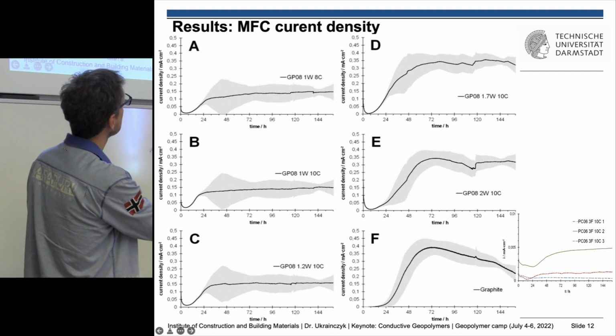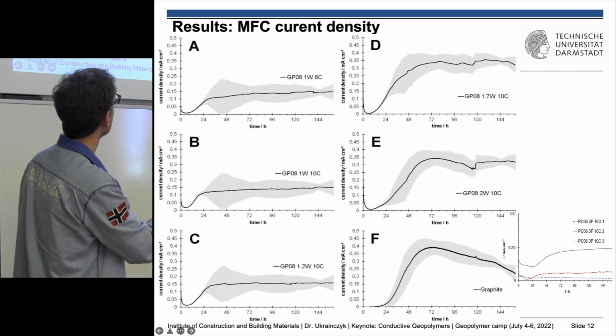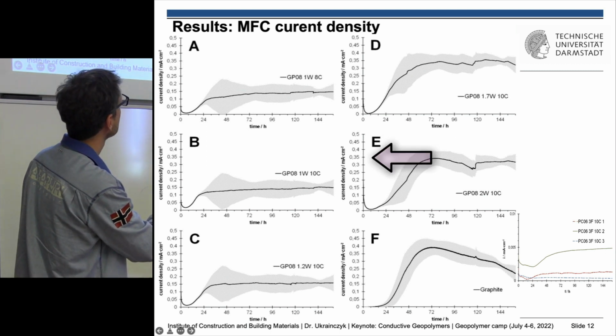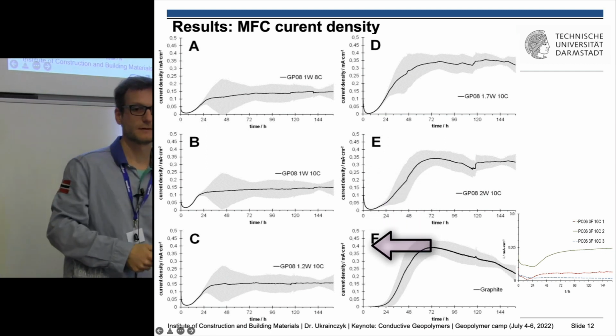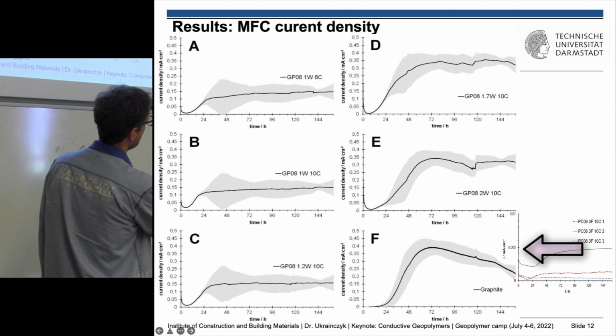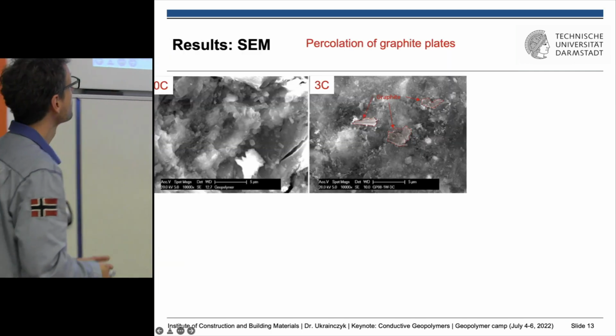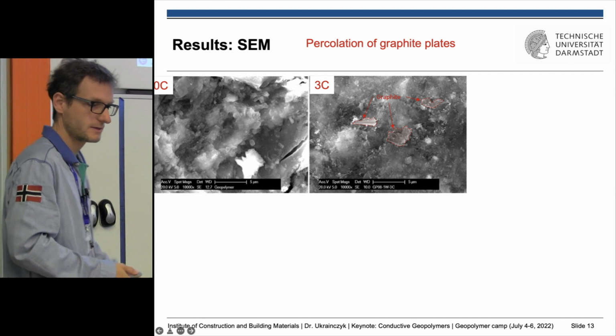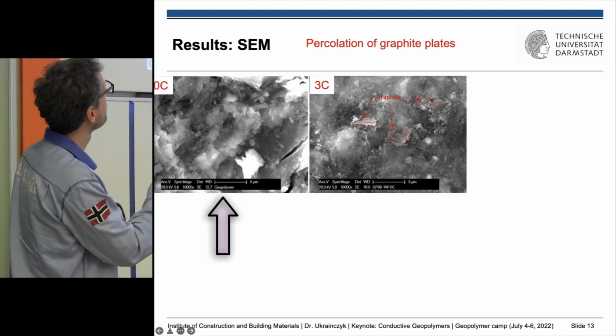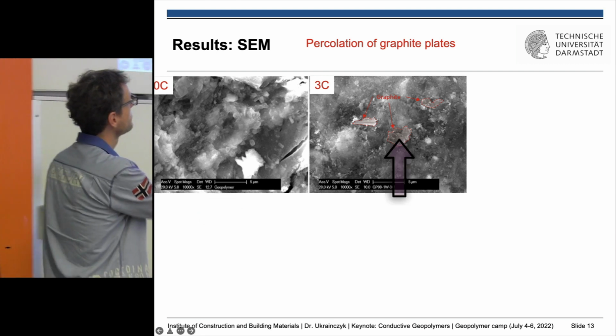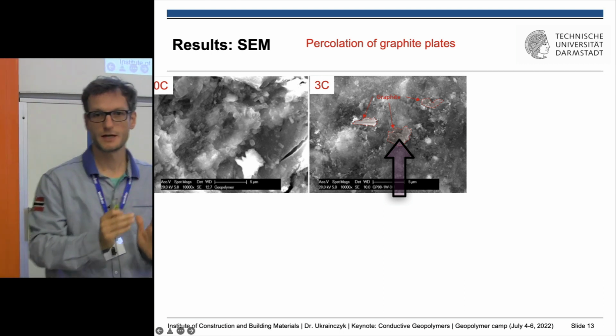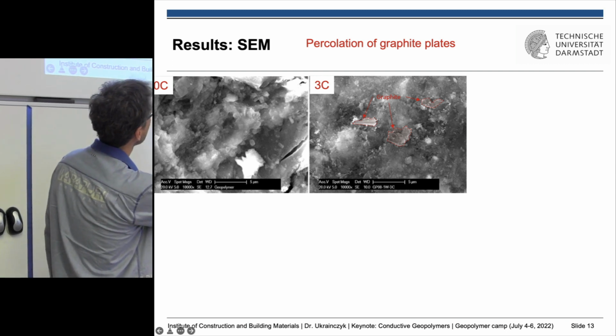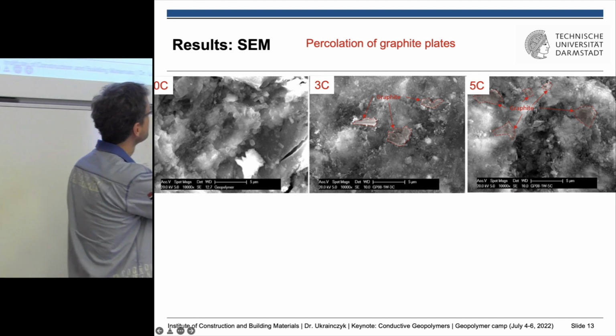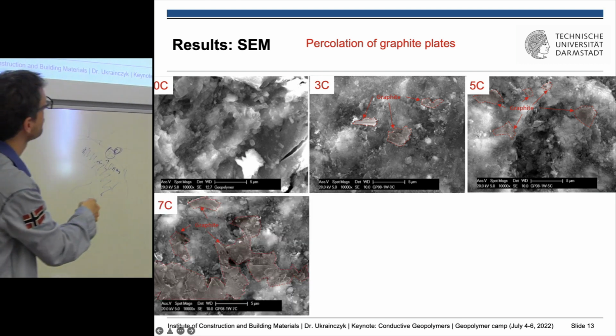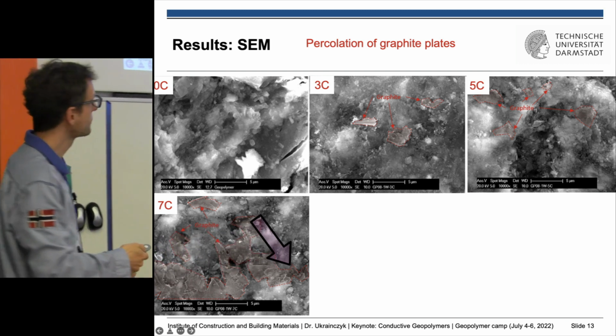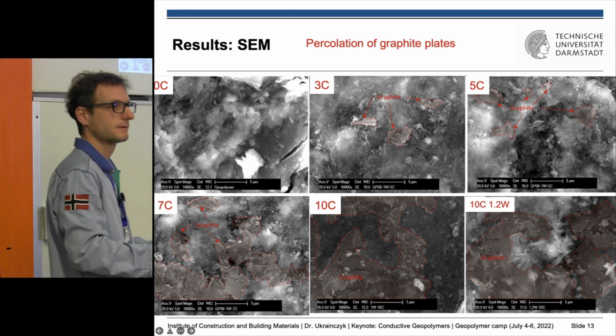So this is the power, the current density around up to 0.4 roughly. And we can see that we reach quite approaching the performance of the graphite reference. For Portland cements, it's really almost nothing, almost zero, 0.005. So now we took some images to see how this graphite percolates. And you can see, this is without graphite. And then we identify the graphite particles because of the edge shape and also the plate structure. And hope you can see them here. But then by increasing the percentage of the volume of the graphite, you can see more and more of them, and they start to be connected. And this is the mechanism for electricity, how they conduct the electricity.